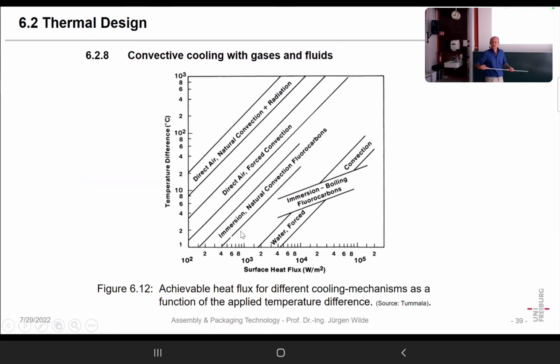Okay, now a last word about convective cooling. So we have already seen some values. That's typically the surface heat flux we can have, that is in watt per square meter, and the temperature difference. Of course, taking temperature difference divided by the surface heat flux, or the slope here, is just the thermal resistance we have. And so we can see direct air, natural convection, forced convection, immersion. Here it was immersion in fluorocarbon. That was done for the first supercomputers. They were just in a certain organic liquid. And so there was convection, not by air, by that organic liquid. But that was a very expensive solution.